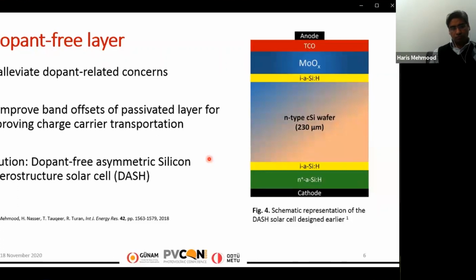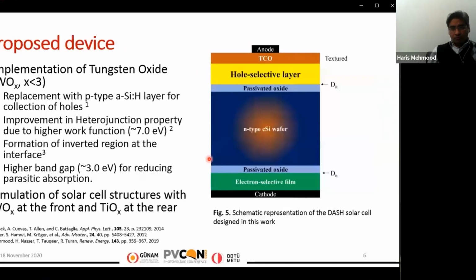In such DASH solar cells, we try to replace the doped amorphous silicon layers with the respective carrier selective films. The hole selective layer will be replaced with molybdenum oxide or some other high work function material, and the n-type amorphous silicon layer will be replaced with some low work function transition metal oxide. So we propose tungsten oxide as a hole selective layer for our structure, and titanium dioxide for our electron selective film layer.